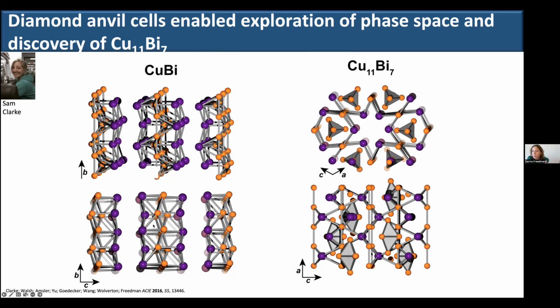We also have this copper-bismuth 1-to-1 binary compound, where you can see that we have these nice layers that are separated by van der Waals interactions between the bismuth atoms. And these, to me, look fairly promising for future exfoliation studies.